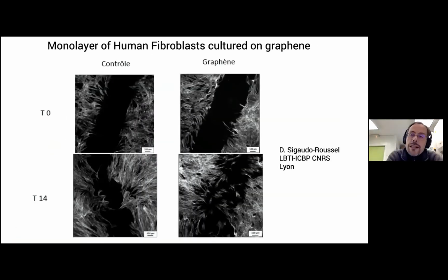So then we decided to look at skin cell culture. This is the human fibroblast. And we mimic a wound here by scratching the layer without scratching the graphene. And you see that on the control substrate, after 14 hours, you still have a gap here. It's a half millimeter gap. In the case of monolayer graphene coated slide, you clearly see that there are cells at the center and there is full proliferation of the system. And a higher density in the beginning. So again, we reproduce that with skin cells.